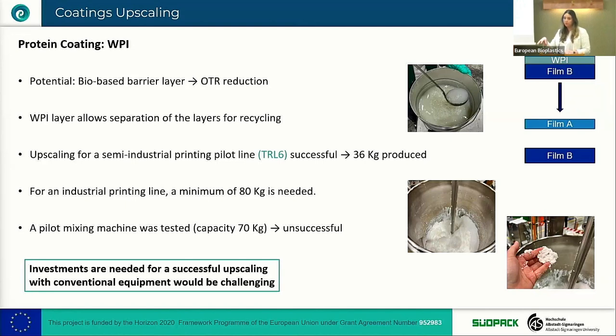We have to do it on the production line where you are printing, because the shelf life of these coatings are very short. With the conventional machinery that we have at conventional converters, it's really difficult to achieve this, because you have to overcome the foam formation, you have to work with really low speeds and control temperature. We came out to the conclusion that some investments must be done, but we are confident these solutions are very sustainable, and still we achieved to do some semi-upscaling of a semi-industrial printing pilot line, producing around 36 kilograms of this coating.